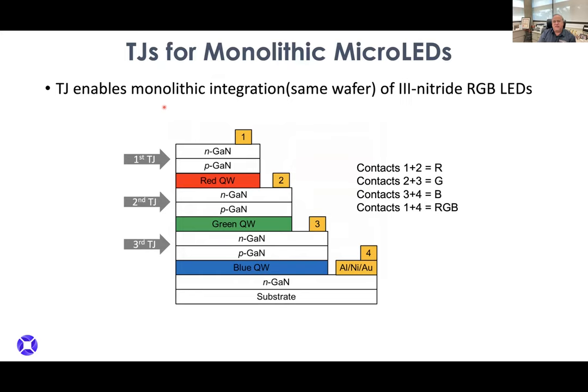The initial idea was, if we can do all three colors with the same material system, then rather than get three different LEDs and put them together on a substrate, you can what's called epitaxially grow. That is, we deposit this in one reactor step. You can actually grow blue, green, and red all on the same wafer. And believe it or not, you can deposit this whole structure in only 4 hours, versus having to get three different wafers and three different epi runs and cut them apart and put them together. So this is our vision for what's called a monolithically integrated red, green, blue microdisplay.